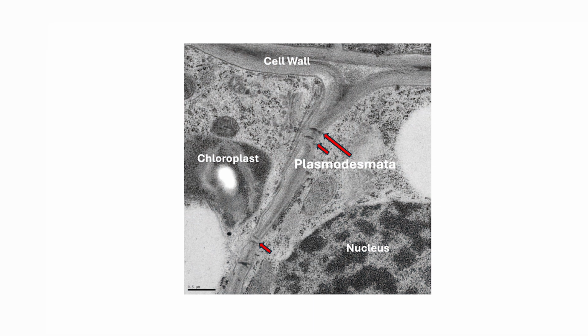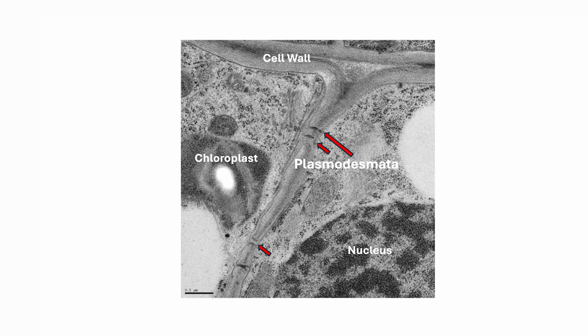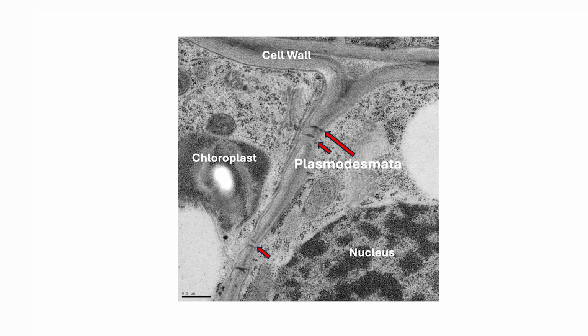In our work, there's two areas of high interest, and one of the things that's driving more efficient scanning is that every plant cell, almost every plant cell, the vast majority of plant cells are connected to adjacent cells by small pores called plasmodesmata. And these pores are around 40 to 50 nanometers in diameter. And so you need an electron microscope to see it. And it turns out that when you look using a transmission electron microscope in an ultra-thin section, you see a handful of them at a time in a field of view.